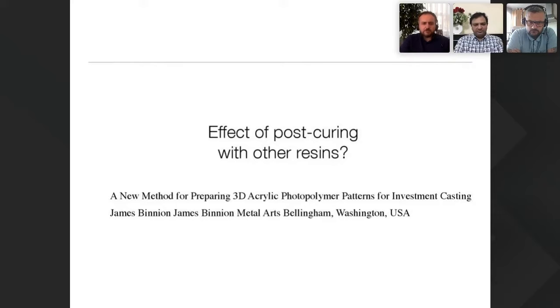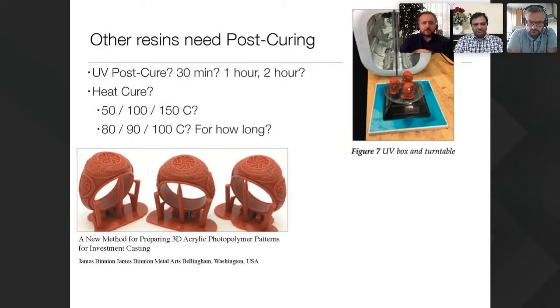Okay, what happens if you post-cure some resins? This is another paper which is very interesting, and we can share it as well. They took a well-known resin in the market and did some casting tests by post-curing for 30 minutes, 1 hour, 2 hours, and they also did some heat curing - leaving it in heat before making the tree. There are different tests there, heat curing and so on.